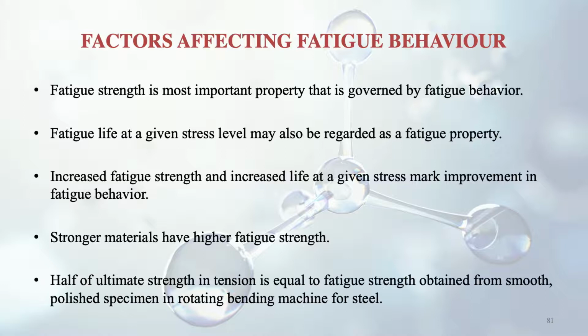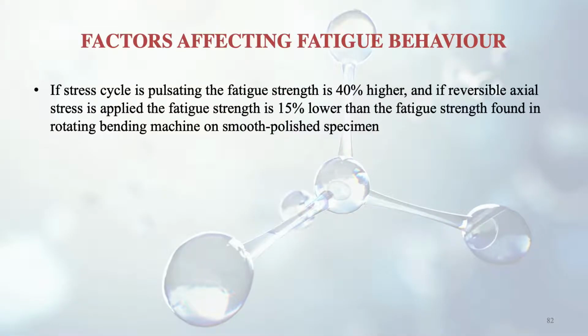Half of the ultimate strength in tension is equal to the fatigue strength obtained from a smooth polished specimen in a rotating bending machine for steel. So it is seen that generally half of the ultimate strength in tension is equal to the fatigue strength for the stronger materials. If the stress cycle is pulsating, the fatigue strength is 40% higher, and if reversible axial stress is applied, the fatigue strength is 15% lower. So we can see here that reversible axial stress is much more dangerous in one sense than the pulsating type of stress, because the fatigue strength is very much lowered in case of the reversible axial stress.